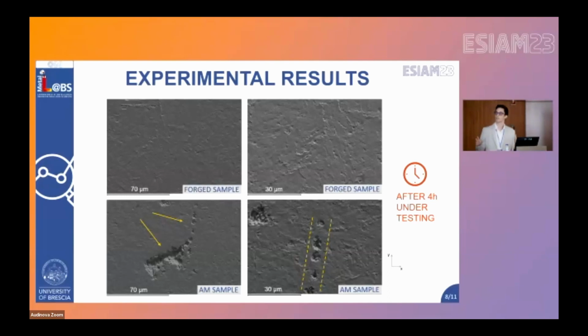On the other hand, at the surface of the additive sample, you can see larger craters. And what's interesting is that some of them seem aligned or to follow some preferential path. So that makes us think that the erosion process starts at weaker points in the microstructure of this sample.